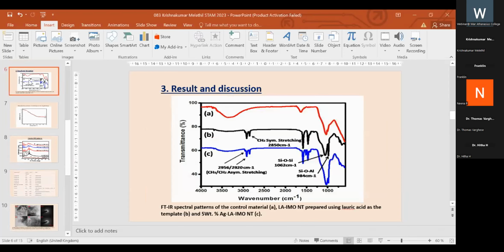And we can go to the results and discussion. Among the characterization techniques, we used FTIR first. In FTIR, we proved that it's a hybrid material, a combination of lauric acid and imogolite nanotubes. In the blank sample preparation, we don't use lauric acid, so it forms a combination of allophane and gibbsite, containing only alumina and silica. There is no formation of imogolite nanotubes, so the peaks are very poor, and there are no organic or lauric acid peaks.